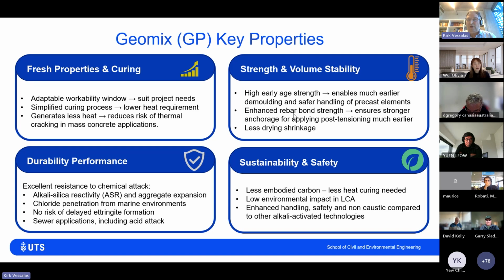There is also very, very good bond strength, and we're about to embark on undertaking some tests in this area at UTS. And the really good thing about this is that you can ensure that you get much better anchorage for applying post-tensioning or pre-stressing much earlier. So instead of waiting for 3 or 4 days, you can apply it, say, between 1 and 2 days if required. Overall, we're also finding that there's less drying shrinkage, and this is all compared to conventional ordinary Portland cement systems using different binary and ternary blends.